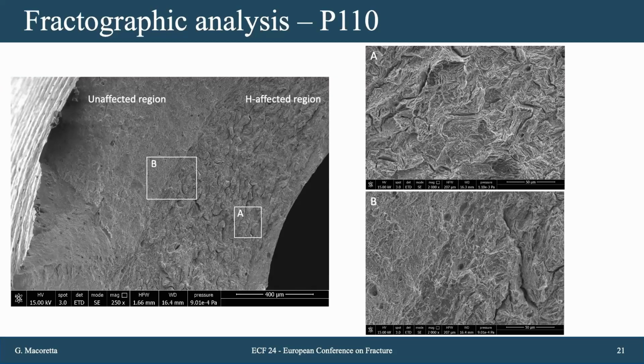If we look at region A, it is the same image that I showed you in the previous slide: a region with transgranular fracture and even some traces of intergranular fracture. In region B, we see transgranular fracture here and here the traces of microvoid coalescence, so the ductile region. So when we reached fracture, hydrogen had affected at least half of the specimen. Then we reach a condition where the cross-section is not enough to withstand the load. In some other portion of the specimen, hydrogen affected an even wider thickness. This is the more conservative region of the specimen, where the unaffected region is wider.